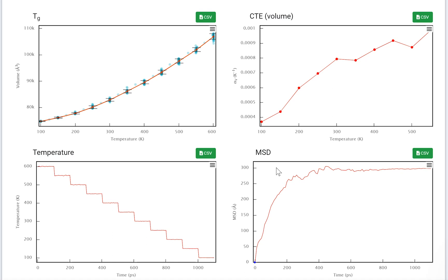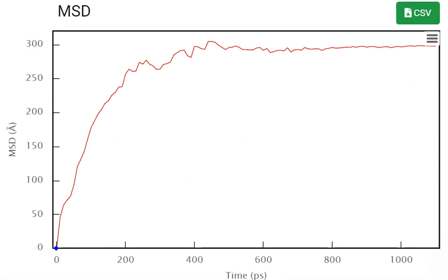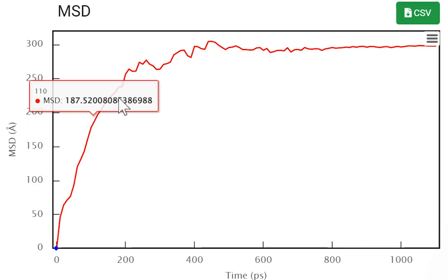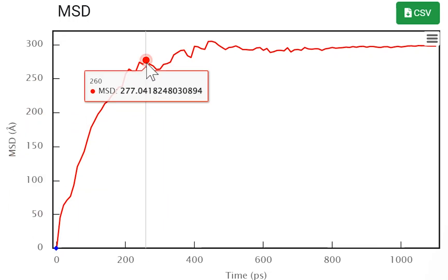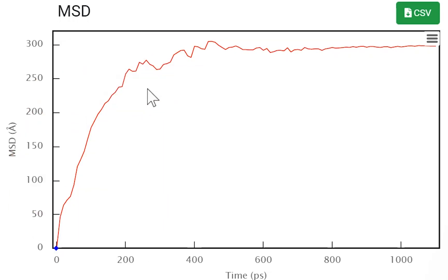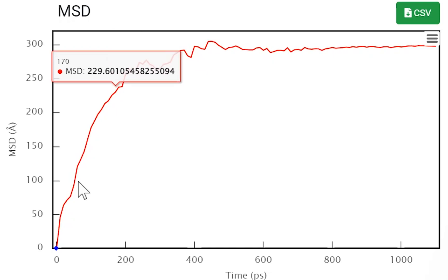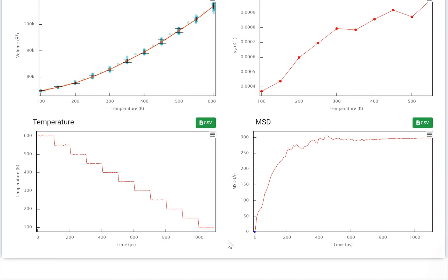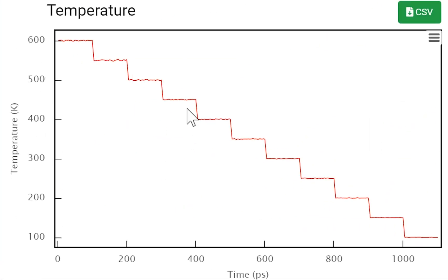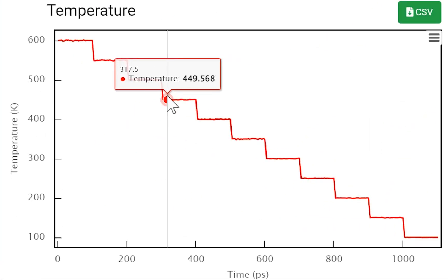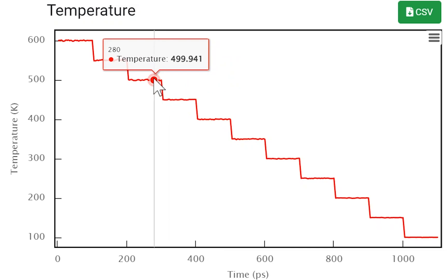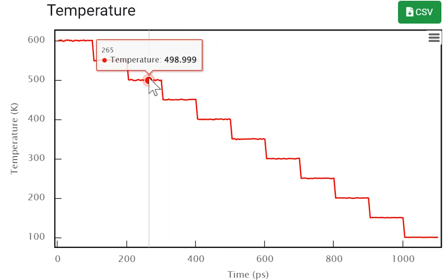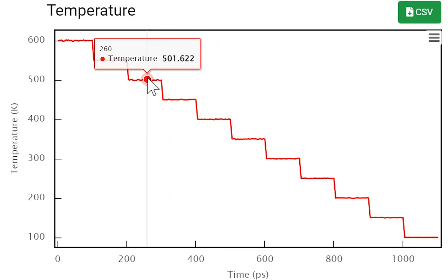We can also find the melting point. Specifically, see the MSD graph. MSD is the abbreviation of mean squared displacement, which means the total amount of the movement of the entire atoms. We can find the atoms move actively before 260 picoseconds, and after is not. So we can consider the before 260 picoseconds range as the liquid. This range is before the 500 kelvin range. So we can estimate the melting point is around 500 kelvin.